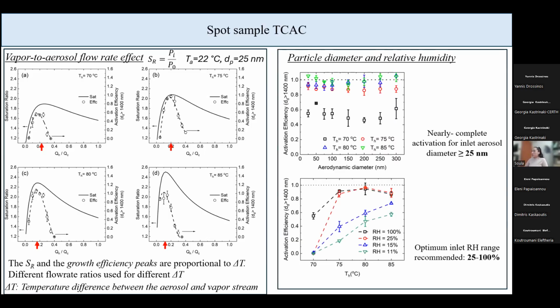The next thing that I tested was the activation efficiency as a function of the aerodynamic diameter of the aerosol that acted as nuclei. And I saw that in most cases at water temperatures of 75 degrees Celsius and higher, we can get nearly complete activation down to 25 nanometers. The optimum inlet relative humidity range that is recommended for this setup was in the range of 25 to 100% for the aerosol flow.